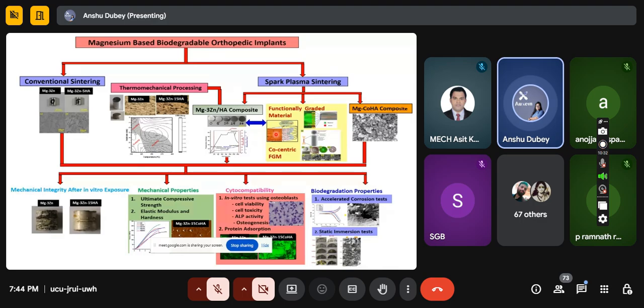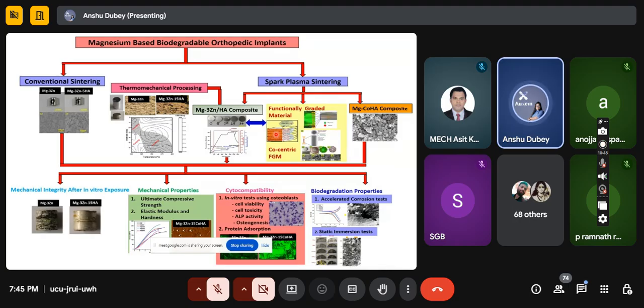Now, if you see the bone anatomy, you will see that it is hollow at the center, with increasing layers. The outer layer is known as cortical bone, and the inner layer is known as cancellous bone. So this is how natural bone looks and how it has been developed. What we tried, which is mentioned here, is a functionally graded material. We tried to make the core similar to the cancellous bone, using pure magnesium, and the outer layers were changed with increasing composition of hydroxyapatite, to mimic the natural bone, so that the bone should feel that this is its natural part.